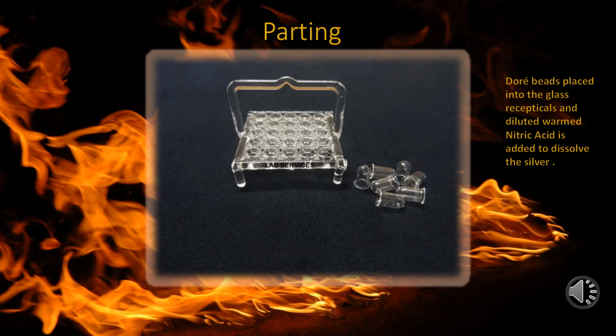The parting is completed using parting cups that are designed for this process or by using glass beakers. After parting, the beads are decanted from the solution and washed with distilled water. If concentrations are large enough for recovery, nitric acid is used. Since gold is a noble metal, it will resist the nitric acid, and the silver, etc. will be dissolved into the acid. The acid solution containing the silver is saved, as the silver can be recovered later. The gold will remain. The purity of the gold will differ depending on the amount of silver concentrated in the bead. This will be explained in a future presentation when cupellation and parting will be discussed in greater detail.